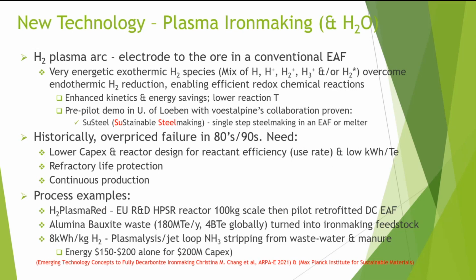Plasma iron making has arisen again. Basically a plasma arc electrode to the ore in a conventional furnace. It's very energetic species of hydrogen that are created, which overcomes the endothermic nature. There are enhanced kinetics and energy savings, lower reaction temperature. There's a pilot demonstration at the University of Leoben with voestalpine cooperating.